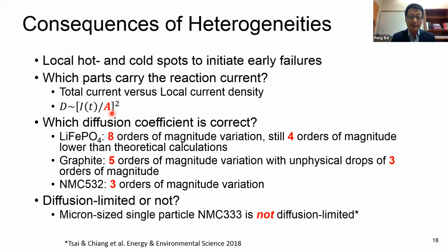And even more recently, the micron-size, single-particle solid solution material, nickel manganese cobalt oxide 333, was determined to be not diffusion limited, right? It's not limited by solid-state lithium ion diffusion. Can you imagine that? It's hard to imagine because everybody would think that ions diffusing through a solid should be really, really slow, instead of a reaction on the surface. But this really matters because it changes the strategy.